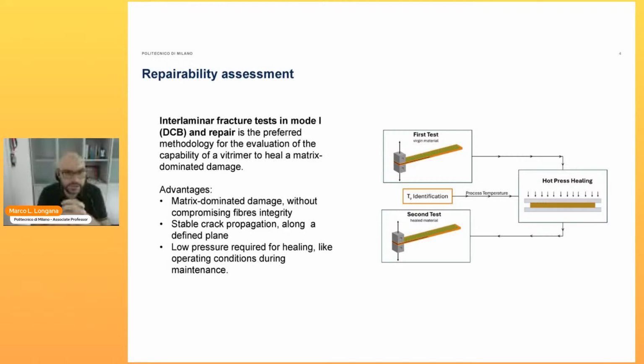Once we have a first evaluation of the mode 1 toughness of our material, we proceed with the repair of the material by simply applying heat and pressure. Of course, we need to be able to identify the correct temperature to apply to our material to be able to repair it. And then we conduct a second DCB test, and from the comparison of the fracture toughness in mode 1 that comes out from the second DCB test, we are able to evaluate or provide healing efficiency for our material.